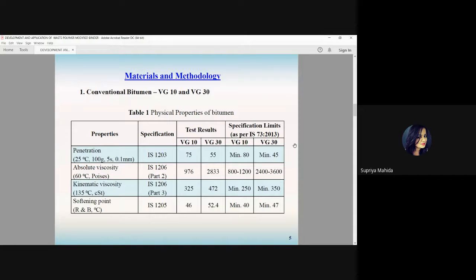We have performed some physical parameter tests like penetration test, absolute viscosity, kinematic viscosity, and softening point, to see whether they are matching the criteria or not. Table 1 shows the results of the various properties of these conventional bitumen grades, and it suggests that they are falling within the specified limit as per IS 73 2013.